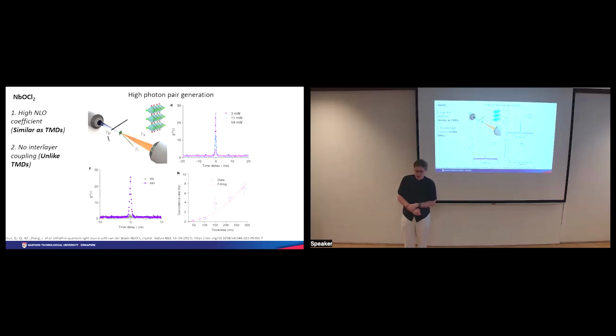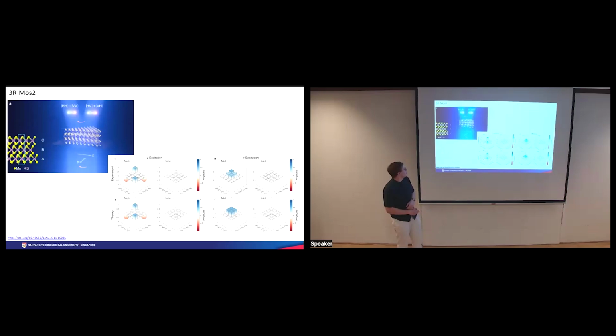And then on the other, which is even more recent, they also used transition metal dichalcogenides, so MoS2. In this case, what they did was fabricate in the 3R phase, because generally the common 2H phase has a cancelling nonlinear susceptibility when you stack the layers together. But with this one, they can actually have a thicker sample; the thickness of the sample is 300 nanometers.